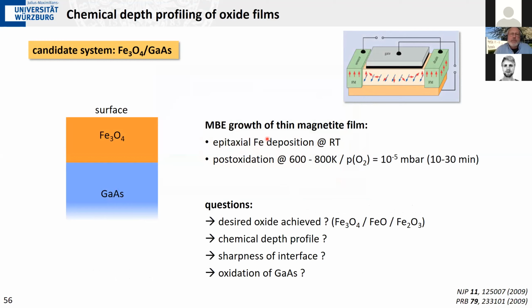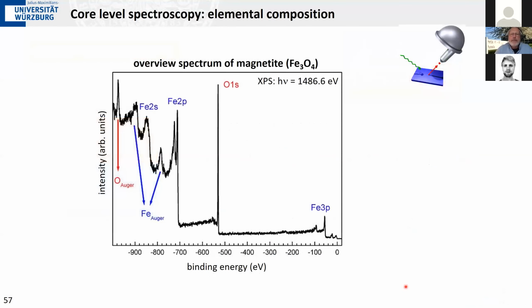And for example, we have done this. We have grown magnetite on gallium arsenide because that is an interface where you would think that this could match as far as lattice constants are concerned. But of course, you run into the problem that here you have an oxide, you create an oxide, here you have a sensitive semiconductor, and what happens when you start oxidizing the iron to achieve this magnetite film on the gallium arsenide? What does the interface look like?